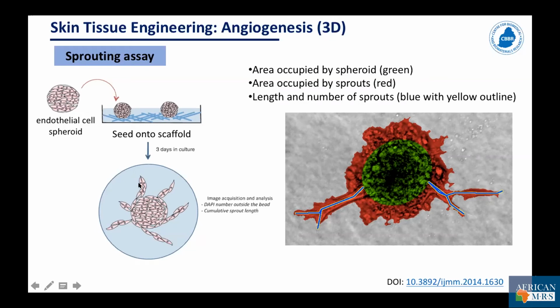So what we can do is quantify the length of the sprout over time. Here we have a colored image showing the sprouts and the area occupied by the spheroid. So in green here is the initial spheroid area, and in red you can see the area occupied by the sprouts, and in blue you have the sprout length. So you can quantify, for example, the area occupied by the sprouts and the length and number of sprouts, and this should give you an indication about the angiogenic potential of the scaffolds.